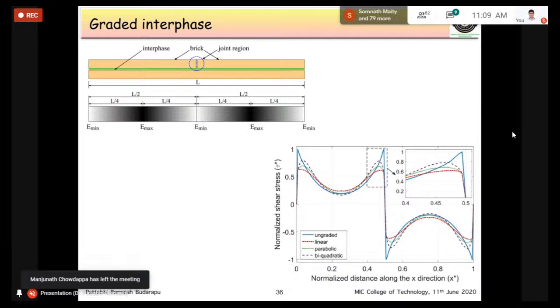So as a result, you can see that the ungraded case has significant stress peaks, and with grading, the stress peaks are slowly reducing. For instance, linear, parabolic, biquadratic grading. In this case, the linear type of grading is working fine. Don't combine this with the three-phase system, because the mechanics geometry is entirely different there. The peak stresses play a role here.